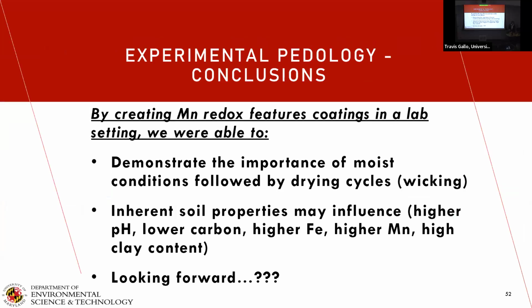So to provide some conclusions of this work, by creating manganese redoximorphic features in the lab, we were able to demonstrate the importance of moist conditions followed by drying cycles. This wicking process, we really demonstrated that well, of what the literature documented, and then showing that in a laboratory setting.